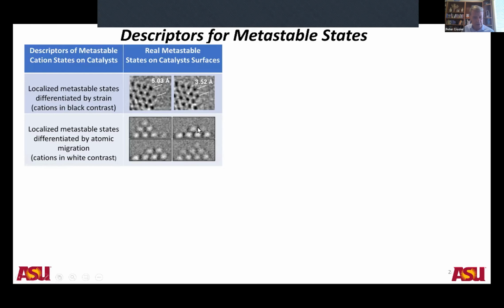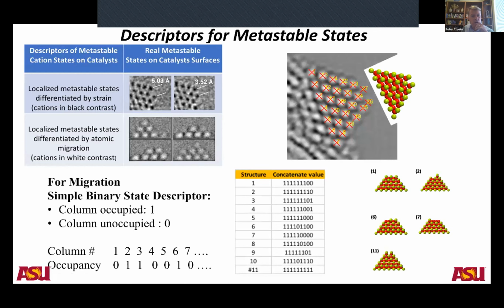So Ramon has been trying to analyze this in some sort of logical way. He's come up with this simple binary descriptor of these metastable states where he uses blob detection to measure the occupancy of each one of these columns. And if the column is occupied, it gets labeled as binary 1. If the column is unoccupied, it gets labeled as binary 0. And he does that for all these columns, 1 through, in this case, 1 through 26. And so each state is then associated with a stream of binary numbers. And here's what these different states look like.